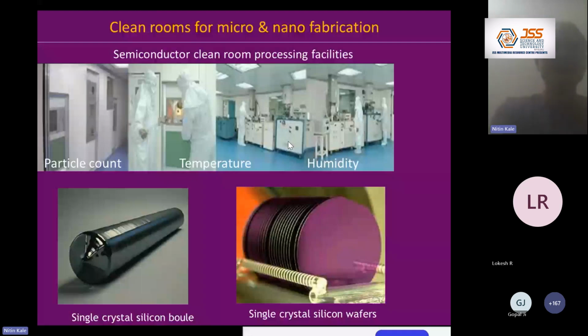In a clean room, what we try to control is the particle count, because these small particles can fall on your substrate, your silicon wafers, and damage the device. You are also interested in controlling the temperature because you are working with many temperature-sensitive materials at a very small scale, so small changes in temperature can produce dimensional changes, and your device can go haywire. Also, you need to control the humidity in a certain range. Too humid, your polymers will not adhere to the substrate. Too dry, they will show cracks. So you need to maintain that as well.